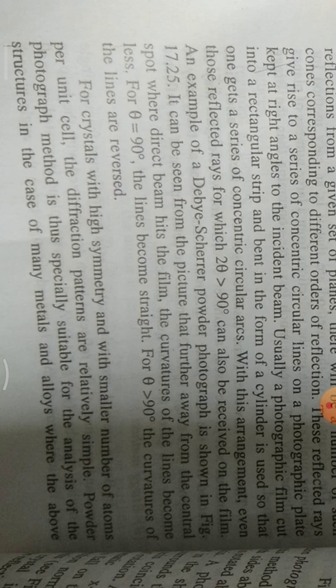With this arrangement, even those reflected rays for which 2θ is greater than 90 degrees can also be received on the film. An example of a Debye-Scherrer powder photograph is shown in this figure 17.25. It can be seen from the picture that farther away from the central spot where the direct beam hits the film, the curvature of the lines becomes less, until for θ equal to 90 degrees the lines become straight. For θ greater than 90 degrees, the curvature of the lines is reversed.